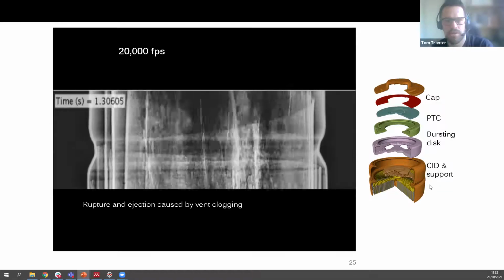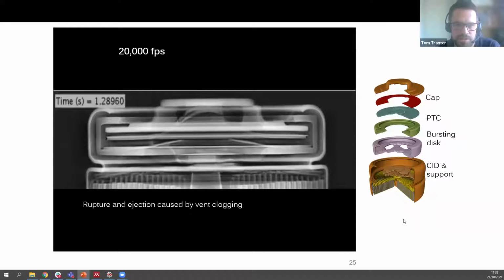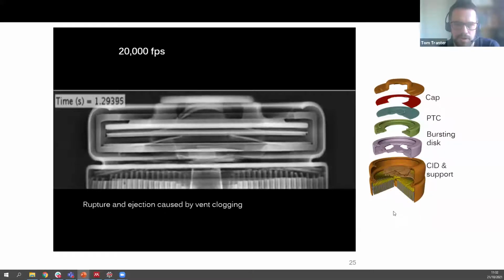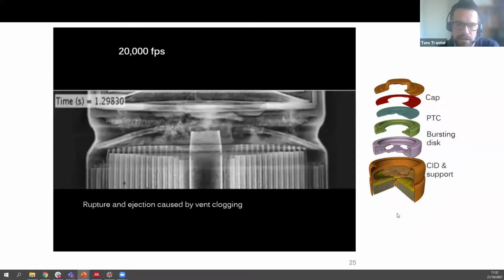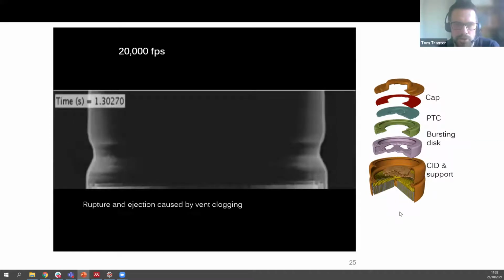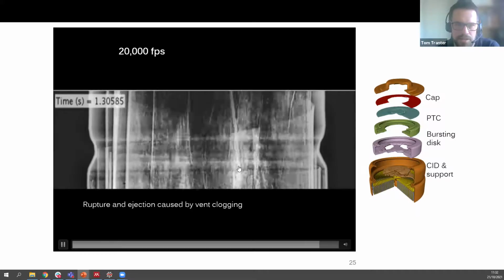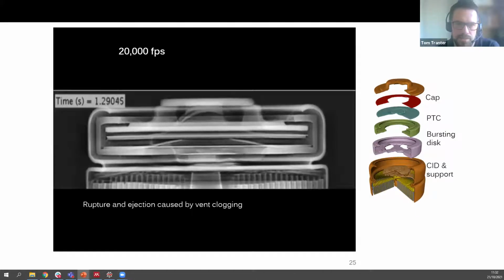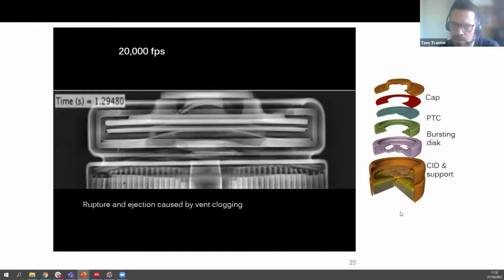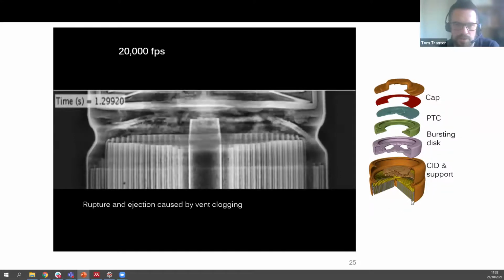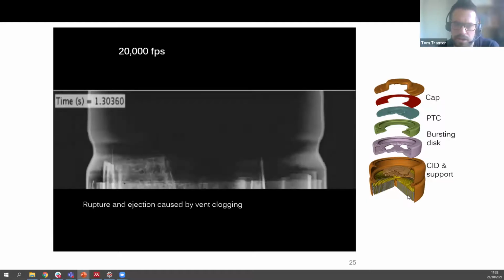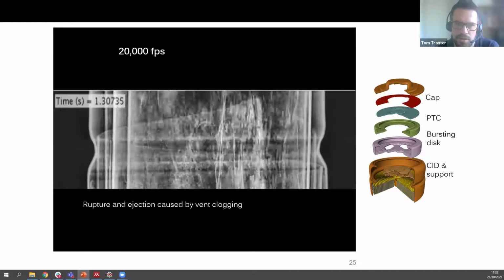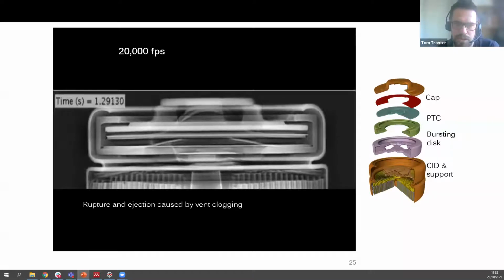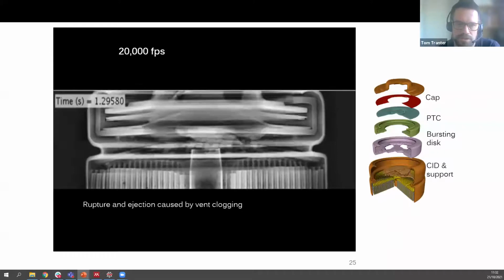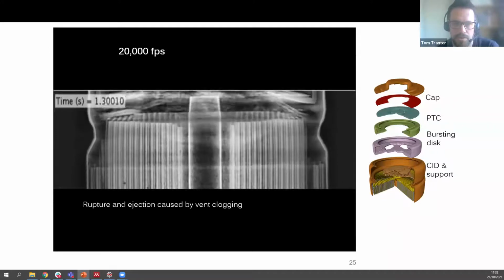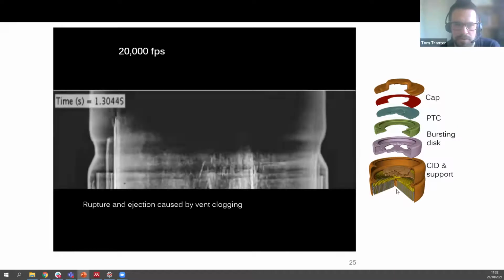This was all captured with pretty high resolution. This is one of the key safety concerns in the battery community: thermal runaway. When you heat a cell or when you penetrate a cell with a nail or something, you short circuit and you get a very high discharge of the cell, which produces a lot of heat. Once the temperature reaches a certain critical point of around 120 degrees, you get reactions in the electrolyte, which then produce heat themselves, and you get this runaway positive feedback, and very quickly the cells can explode. So thermal management is key.